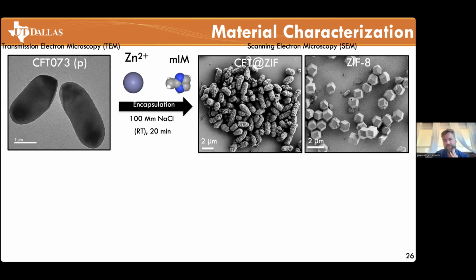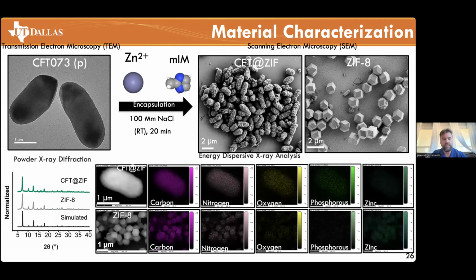This is distinct from what ZIF-8 looks like normally. The normal crystalline ZIF-8 that didn't grow on anything is on the right here, and you can see just large rhombic dodecahedral crystals. If we look at the characterization, the surface coating of ZIF is crystalline, and that matches up perfectly with simulated and pristine samples. And you can look at the distribution of elements over the surface, and you can see that essentially everything's all there, as you would expect.